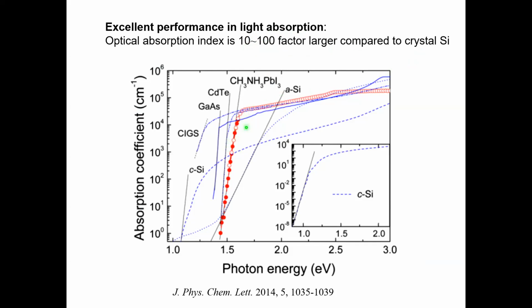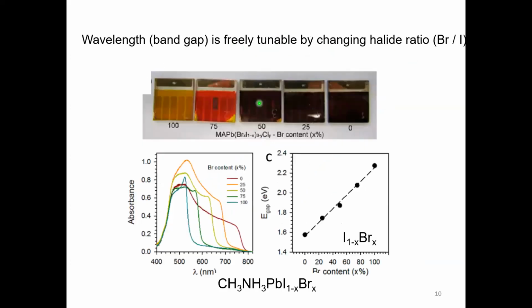This is the crystalline silicon curve and perovskite here. So a very thin layer of perovskite can absorb sunlight. What is the thickness? It is less than 1 micron. Also, the wavelength responsivity is tunable by just changing the halide element, the ratio of bromide and iodide. So we can make all the colorful variations of perovskite semiconductor.